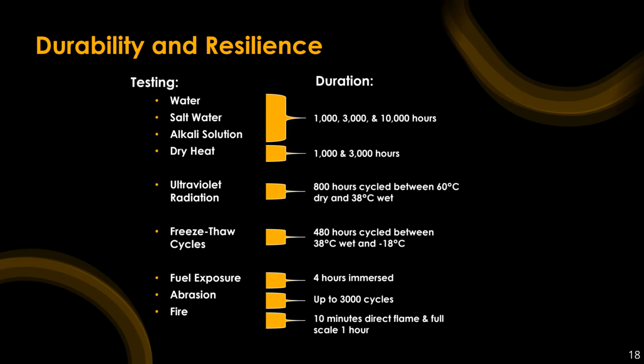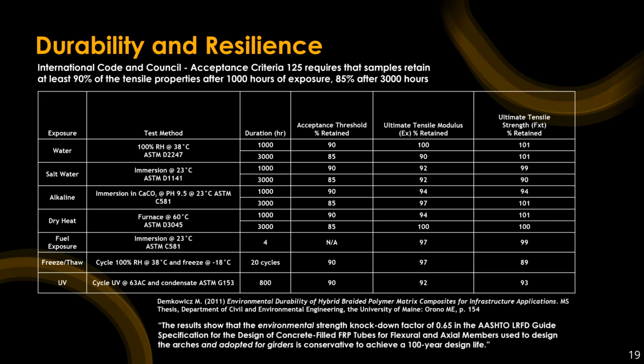The way that acceptance criteria works is that the samples are exposed to these different environmental exposures for different durations, and then they must maintain at least 90% of their tensile strength and stiffness after 1,000 hours of exposure, or 85% after 3,000 hours. This matrix shows the durations and the acceptance threshold, and the materials that we utilize, both the tensile strength and tensile modulus, exceed all those thresholds. Some of these were actually tested beyond the thresholds that were listed, just to see what the correlation might be. One of the conclusions that we can draw is that the environmental strength knockdown factors that we utilize in design, which are pulled from the AASHTO LRFD Guide Specification for the Design of Concrete-Filled FRP Tubes, are conservative to achieve a 100-year design life.